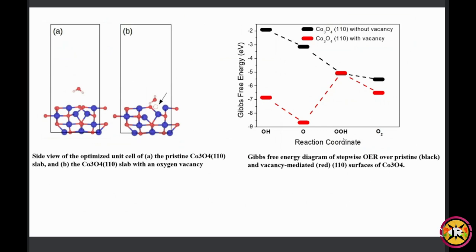Now coming to the theoretical part. Some DFT calculations we have done, and from figure 1 we can see in A, where there is no oxygen vacancy, only pristine Co3O4, O2 is coming here. But in figure B, where this dotted line is showing the oxygen vacancy, H2O is coming more towards the Co3O4 due to the vacancy. And when we calculated the Gibbs free energy versus reaction coordinate, we observe when there is no oxygen vacancy, this path needs higher energy, but with oxygen vacancy, it needs lower energy.